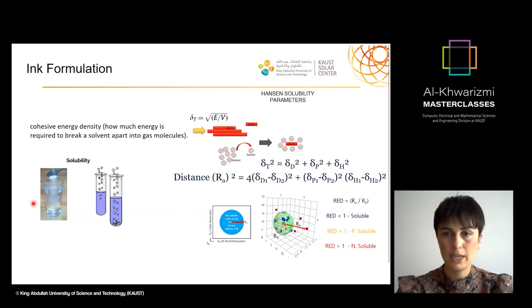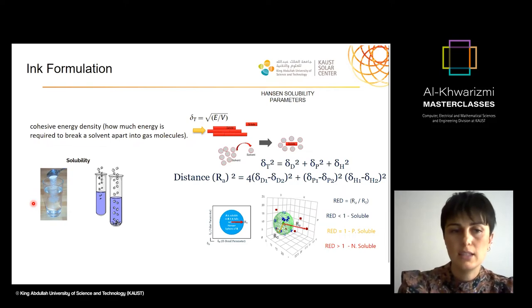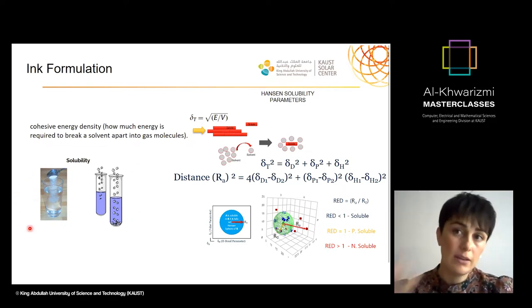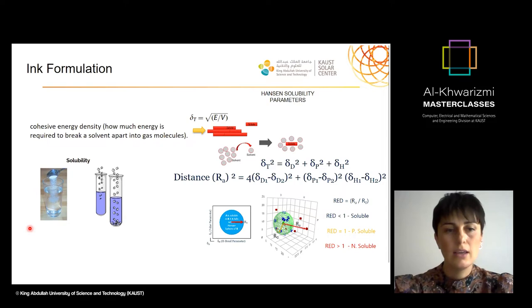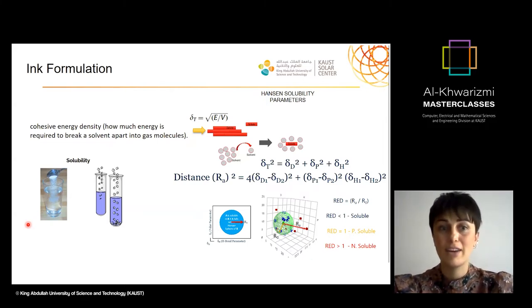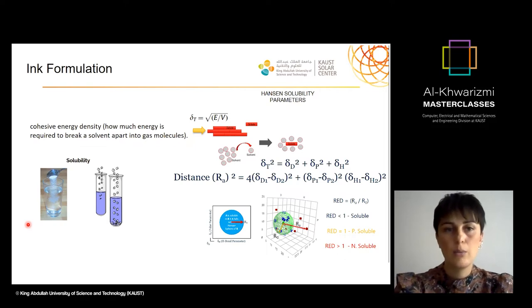So how do we formulate our ink? Because that is one of the keys, as I said, in inkjet printing. One way to look at it is you can calculate the solubility of your material in that particular solvent, in several ways, or a very easy way as well, and look when it starts to precipitate and centrifuge, etc. However, if you're using new and novel materials and they're very expensive, you don't want to waste all this material. Instead, you can use Hansen solubility parameters and you can predict the solubility of your material. That will really help you in order to print effectively.